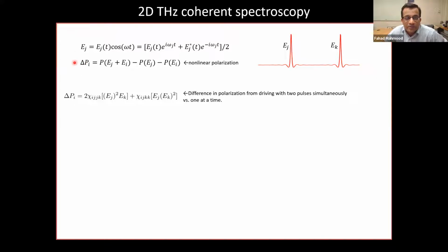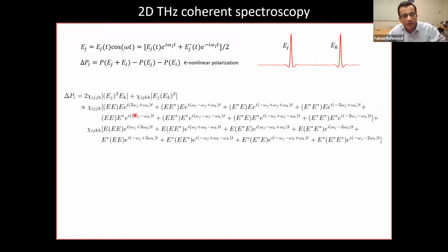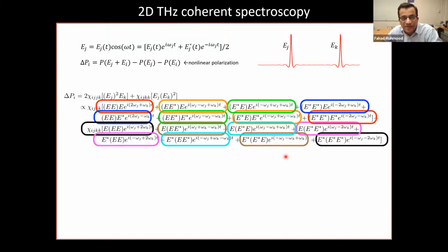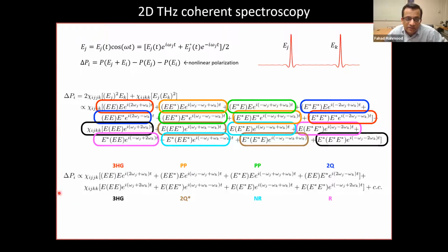So in a very simple case, write down your electric field that's incident on the sample, calculate what the nonlinear polarization of the material would be, and then express that nonlinear polarization in terms of different frequencies of these two electric fields that are going into your sample. Obviously, this is a very complicated expression. So rather than going over it step by step, what I want you to take away is that if I express this nonlinear polarization as a function of these frequencies, you can see that there are different types of responses present in my experiment, and they will occur at different combinations of these frequencies. So for example, there might be a sum frequency here, there might be a difference frequency over here, and that would allow me to distinguish between these different responses. And they will imply different things about the material system in terms of scattering rates.